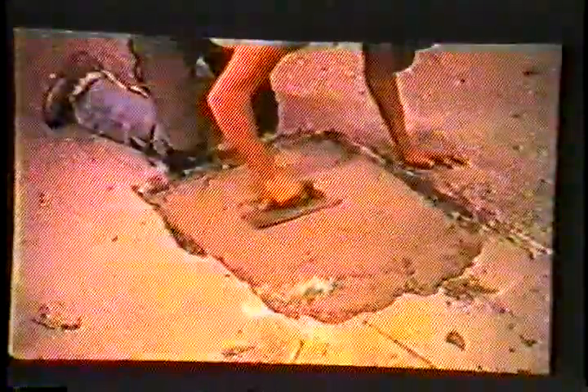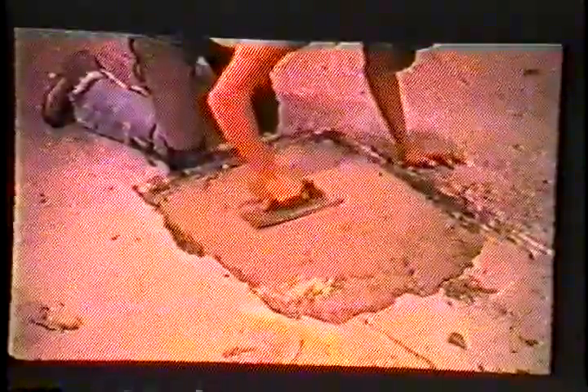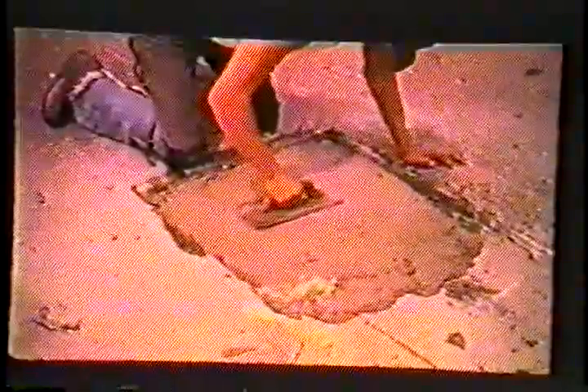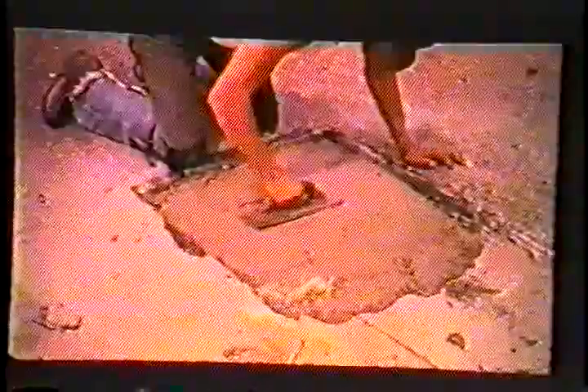Work the concrete with your shovel to eliminate voids and work the concrete around and under the rebars. Your setting time is as short as 15 minutes, so you can't waste time getting the mix in place and finishing. Do your finishing work as soon as possible and don't overwork. If you continue working after the concrete takes its initial set, you will damage the surface.